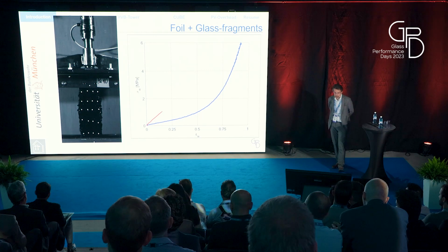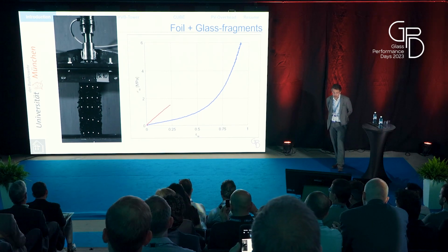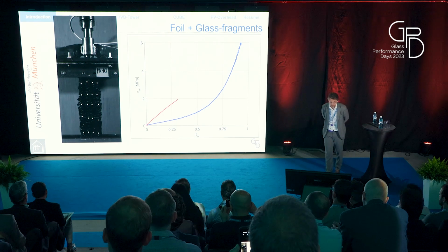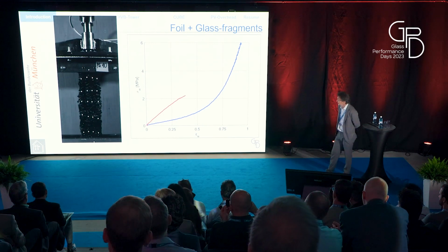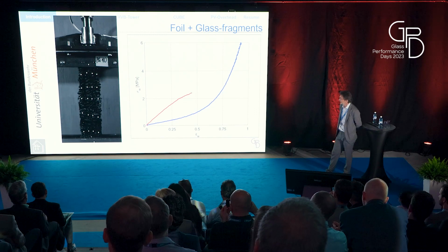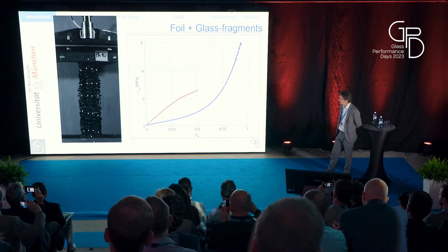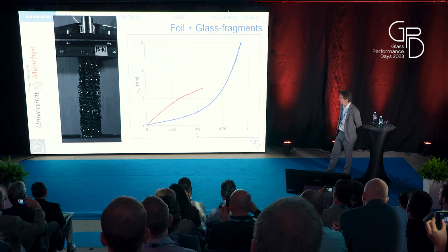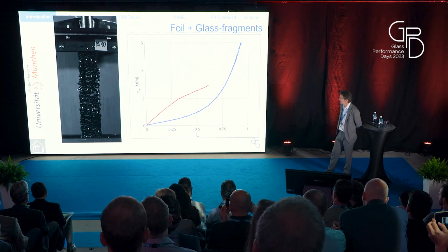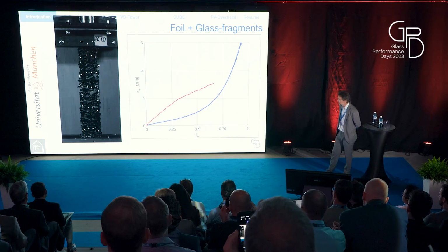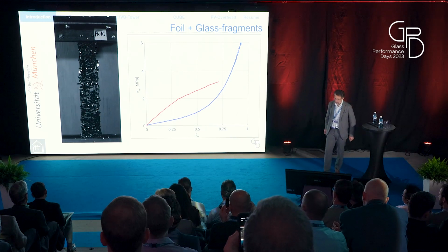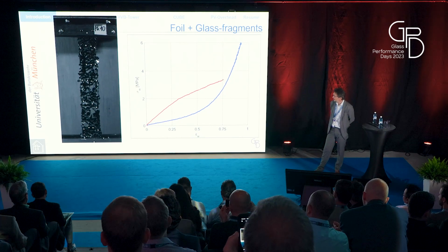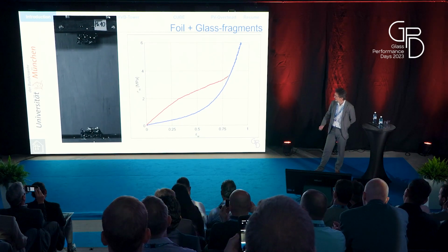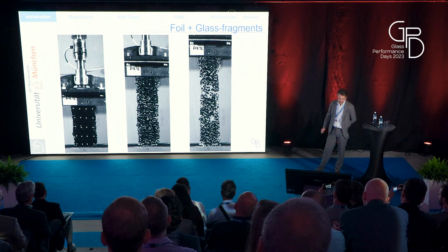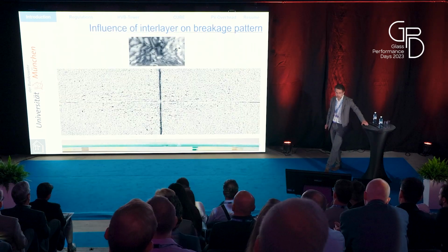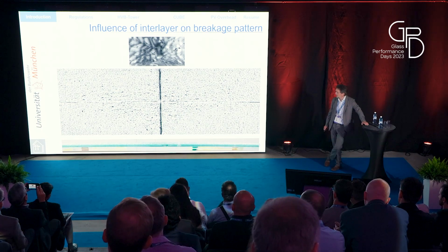So this is fully tempered glass, broken situation, and you see the stiffness, of course, is a bit higher, or not only a bit, it's quite a lot higher. And as the deformations get bigger, of course, the share of the glass material gets lower, and the curves more or less connect again. Glass pieces fall off and no longer contribute to the strength. And another question we just worked on was, is there influence of the interlayer on the breakage pattern?